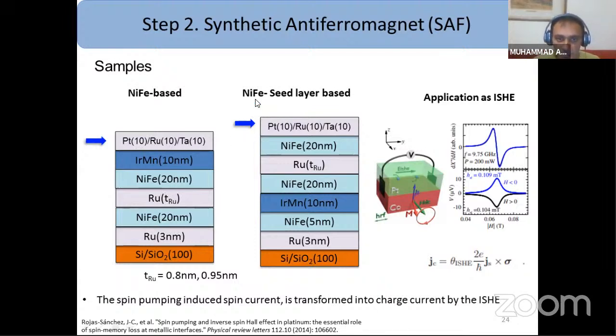Here I have also produced a synthetic antiferromagnet with nickel iron at the top. You can see here, this system can be used with heavy metals at the top. This system can be used to measure the inverse spin Hall effect, that is, spin pumping with the help of VNA FMR. We pump the spins into the heavy metal and then measure the charge current from this heavy metal.